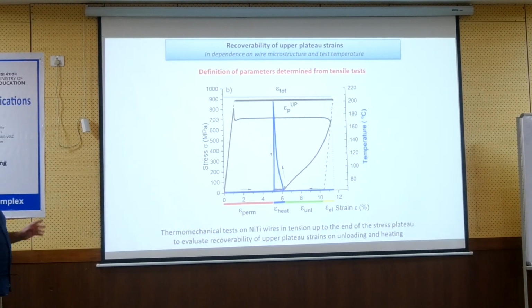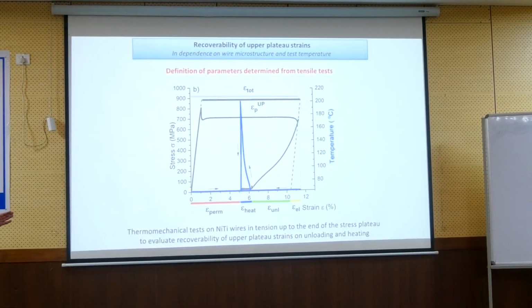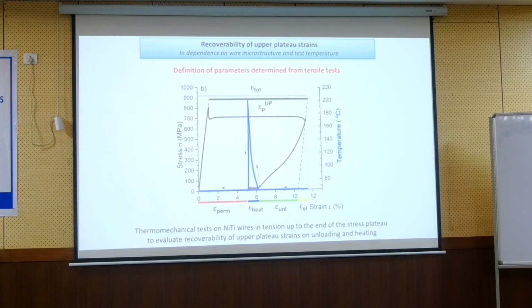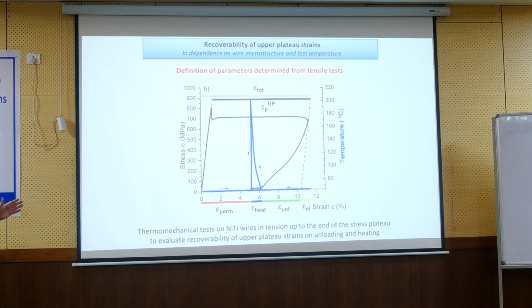discuss some of the specific things in more detail, and this is this plateau length. So we published an article about the analysis of this plateau length, and the work was done by doing systematically the test only till the end of the plateau, like we normally do in the shape memory field. Yeah? So in the shape memory field, you are loading the wire to the end of the plateau, then unload, and if there is some unrecovered strain, we heat the wire up to 200 Celsius and unload. Yeah? So